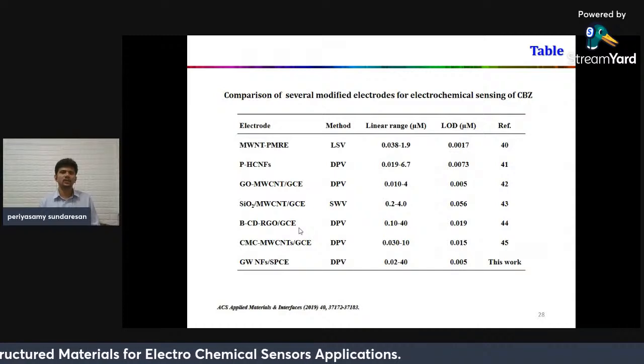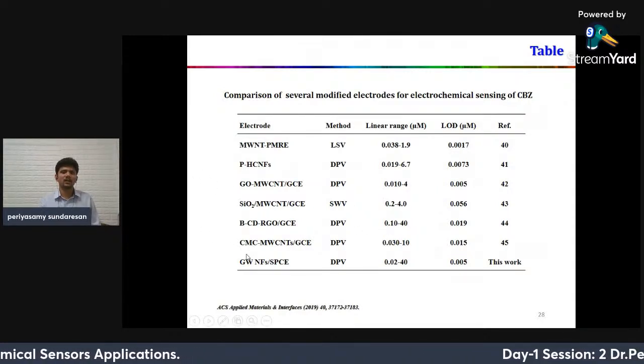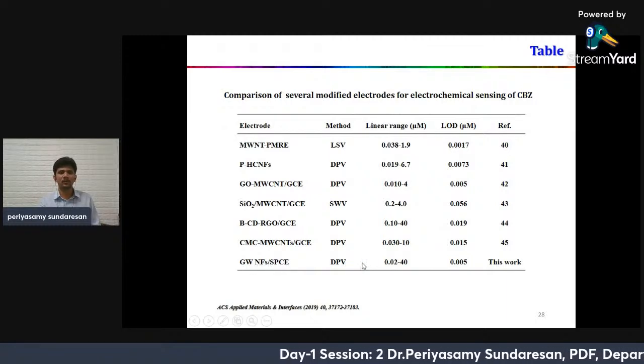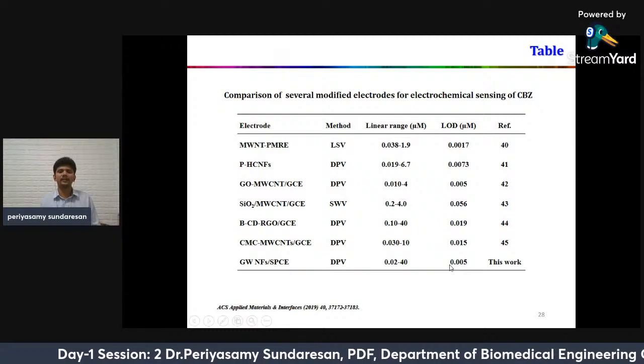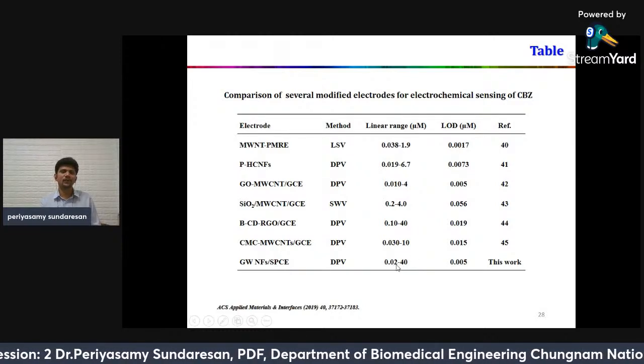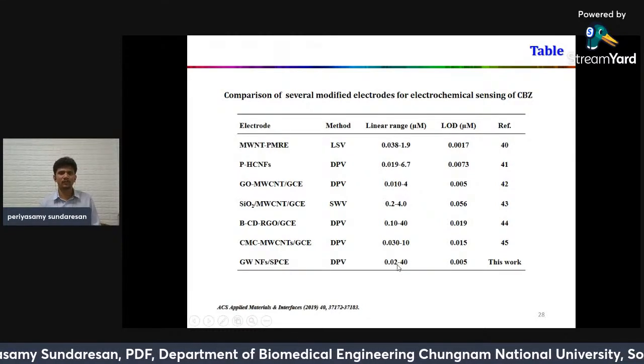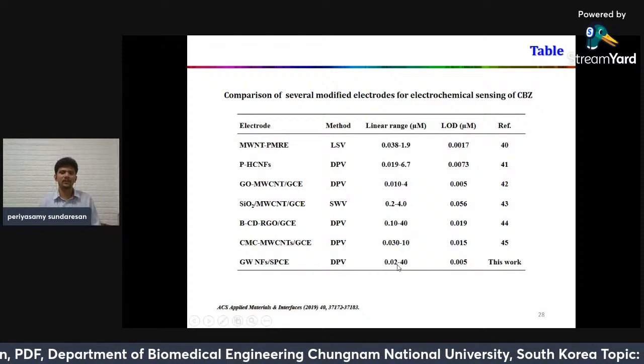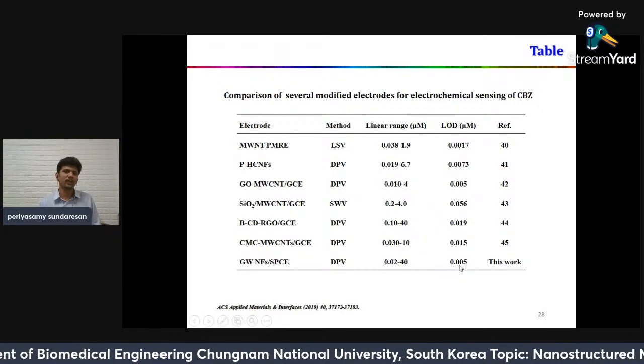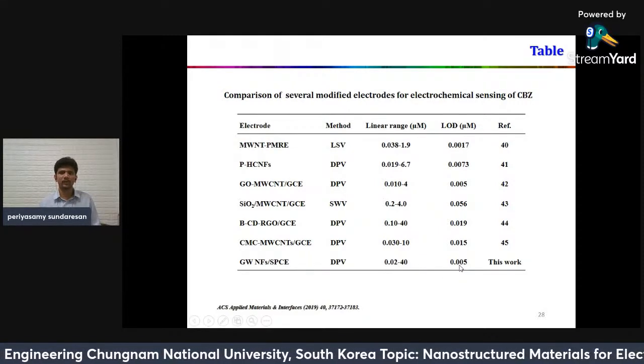Compared to the previous literature's work, the previous modified electrodes, the prepared gadolinium tungstate nanoflakes give a good response for carbamazepine electrochemical sensing. It gives a linear range of 0.02 to 40 micromolar, and the lowest detection limit is 0.005 micromolar.